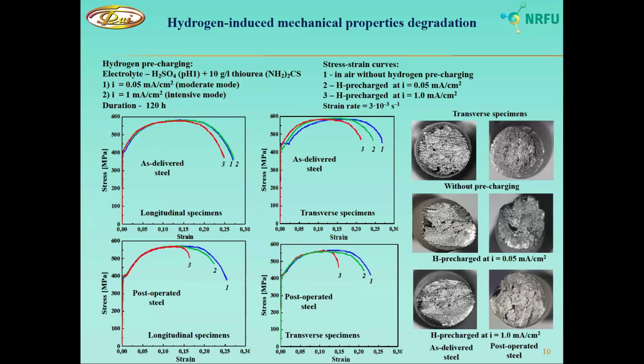On this slide, we can see stress-strain curves for the as-delivered, post-operated and hydrogen-free and charged specimens. And we can see that there is no remarkable difference in strength properties for the studied experimental conditions, as well as steel state and orientation of specimens relative to the rolling direction. And plasticity for hydrogen pre-charged specimens is decreased, especially for the operated metal.